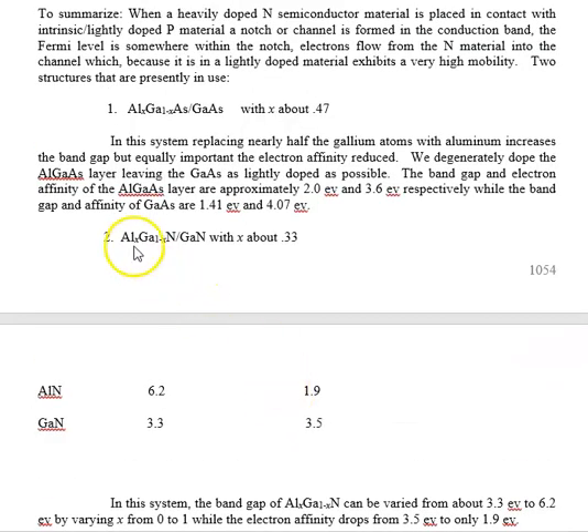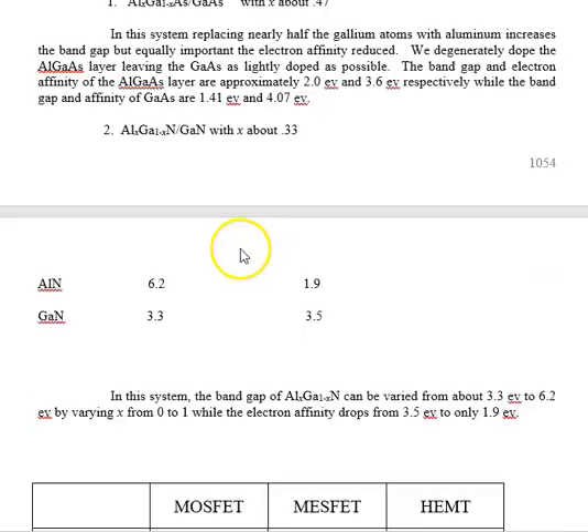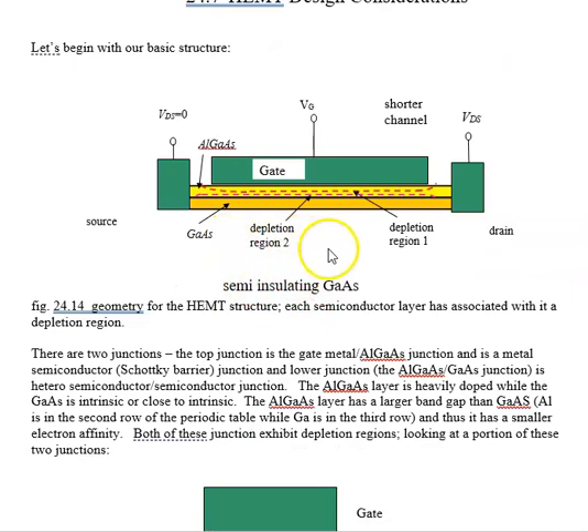I should mention one more thing. I probably should have mentioned it back here. Unlike the AlGaAs, we are not able to grow gallium nitride bulk. So we generally deposit layers, first of gallium nitride and then of aluminum gallium nitride, one on top of the other. And the substrate is semi-insulating silicon carbide. And I believe sapphire is also used. So that's just a point of clarification there. If this was a GaN system, this would not be semi-insulating gallium arsenide. It would be semi-insulating silicon carbide, which is also reasonably expensive, and we certainly don't get it in 12-inch or 15-inch wafers. I think we may be up to 4-inch wafers these days.